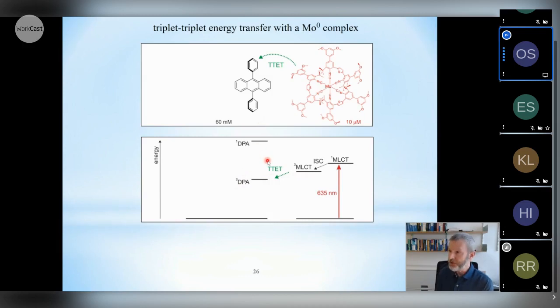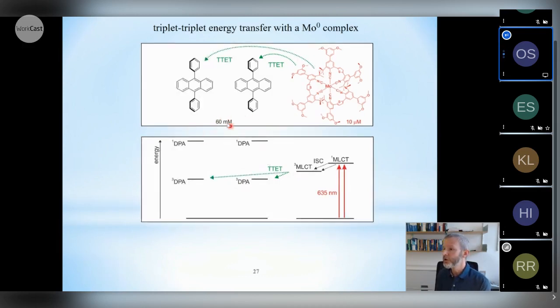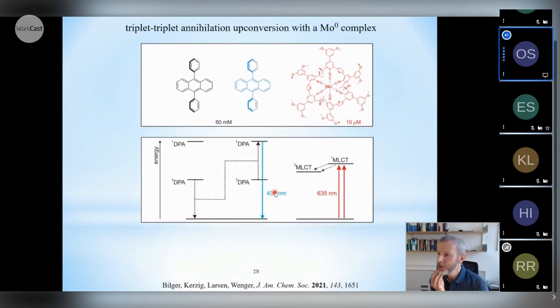And you can do this many times if you have a sufficiently high concentration and sufficiently high photon flux. You can re-excite this all the time and then build up a fairly large population of triplet excited diphenylanthracenes. And every once in a while, two of such DPAs will undergo triplet-triplet annihilation upconversion. And one of them will return to the electronic ground state, whereas the other will be upconverted to the fluorescent singlet excited state. So you get one blue photon out of two red input photons here. And you can study the efficiency and power thresholds into the linear regime. Jakob Bilger did this along with Christoph Kerzig and Chris Larsen in their studies.